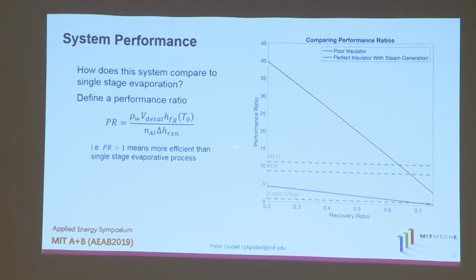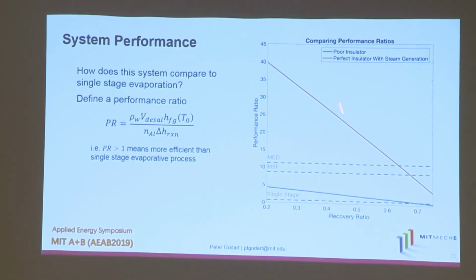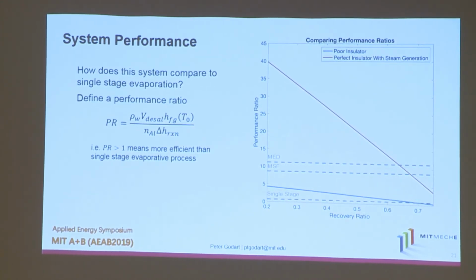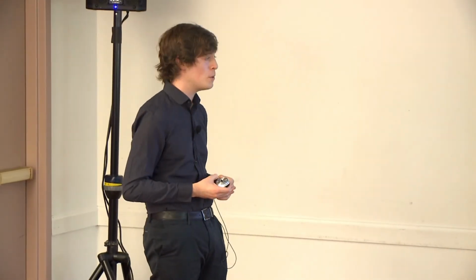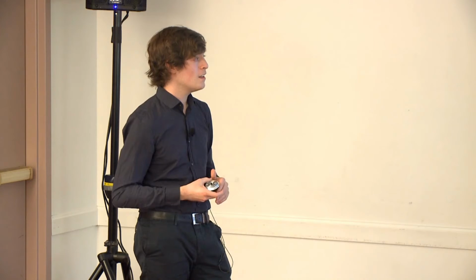And to give you a sense for the state-of-the-art multi-effect distillation systems and multi-stage flash systems, which continuously recycle the latent heat of the water that you evaporate, those only achieve performance ratios in the range of 8 to 12. So this has the potential to do much better than even those state-of-the-art thermal desalination systems. Wherever you might have access to scrap aluminum and you need water and you have access to salt water, this might actually be a good process to do not only for disaster relief, but also for large-scale desalination as well. And again, that depends on how much aluminum you have available.